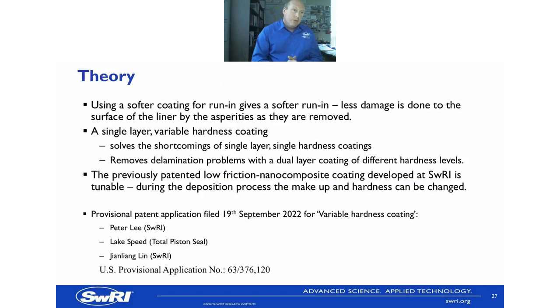So we came up with the theory: using a softer coating for run-in gives a softer run-in, so less damage is done to the surface of the liner by the asperities as they're removed, and a single layer variable hardness coating might be possible. It would solve the shortcomings of the single layer, single hardness coatings, and it would remove the delamination issues of the dual layer coating.